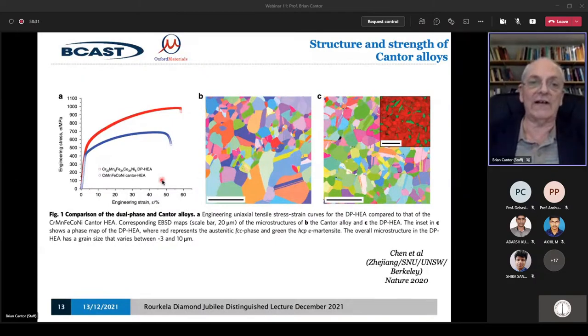This is the original Cantor alloy. This is a slightly improved Cantor alloy. It turns out there's more than one Cantor alloy. There's many of them. I'll show you that in a minute. This is a slightly different composition Cantor alloy. But again, a single phase FCC structure with some similar components with different composition. So these are just two examples. And there's lots and lots of Cantor alloys with different compositions. It turns out they all have strengths in the range half to 1 gigapascal and ductilities in the range 50 to 100%. And that's the best of any materials going.